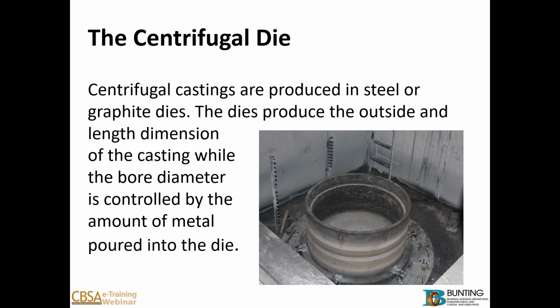Centrifugal die, that's obviously what we're using to make these castings. Centrifugal castings are produced in steel or graphite. It just depends. There's different reasons why we go different ways. The dies produce the outside and the length dimension of the casting. Again, the ID of the mold establishes the OD of the casting, and the same with the length. So in order to determine the ID, it's a matter of how much metal you pour into that die. So the OD is fixed, the length is fixed, and the ID is proportionate to how much metal you pour into it.